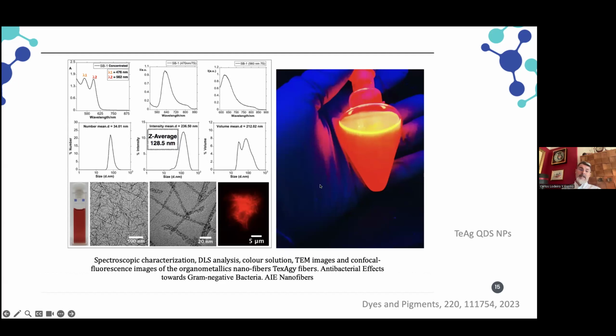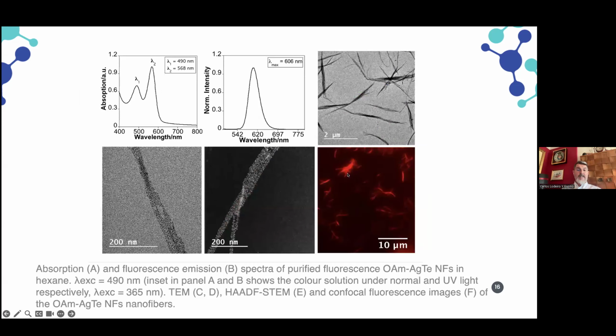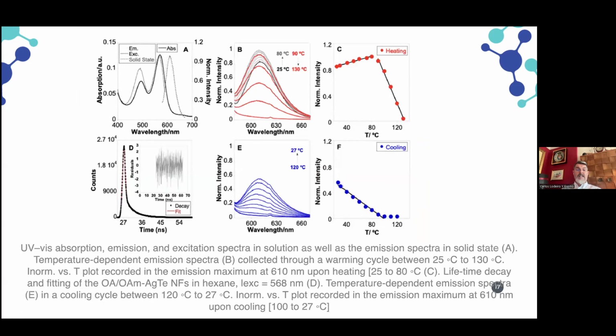So these particles that are formed are at the level of nanoparticles with dimensions around 230 nanometers. However, it's very interesting because, once we modulated the system, we can recognize these single white dots present in the center of this slide, which are the silver nanoparticles. In this case, we observe that they are not completely spherical. We observed that these emissive materials are formed by silver tellurium quantum dots, and these silver tellurium quantum dots are very sensitive, for example, to temperature.